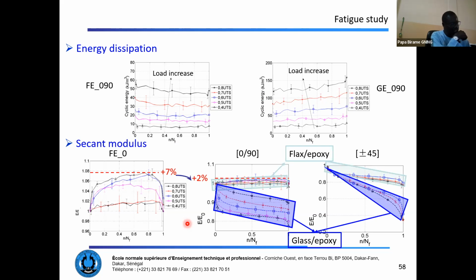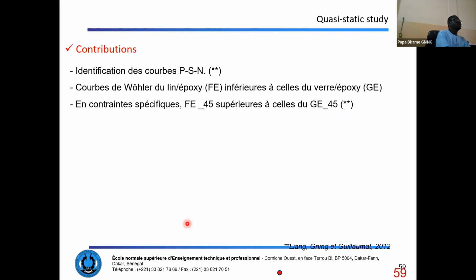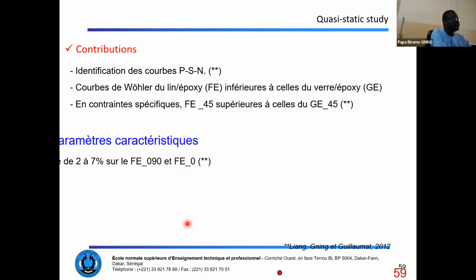We saw for glass epoxy composite, the more they are loaded, the more the hysteresis loop increases, and the more the slope of the hysteresis loop diminishes. So we can note that the fatigue behavior of flax epoxy composite is comparable to the behavior of glass epoxy. The Wöhler curves of flax epoxy are lower than the Wöhler curves of glass epoxy. But for plus minus 45 oriented fibers, flax epoxy presents better specific fatigue behavior than glass epoxy.